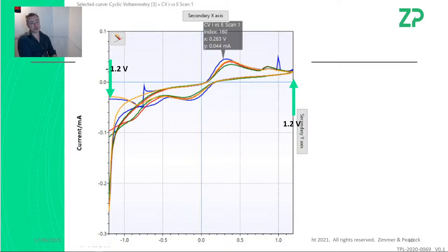Power is equal to voltage times current. So in an extreme here, they've got a current of minus 200 microamps. So it's essentially just gone too wide in this voltage window when doing the voltammetry, and in the negative voltage region, they've generated a lot of current. And it's that passage of current that will have caused the darkening of their counter electrode.